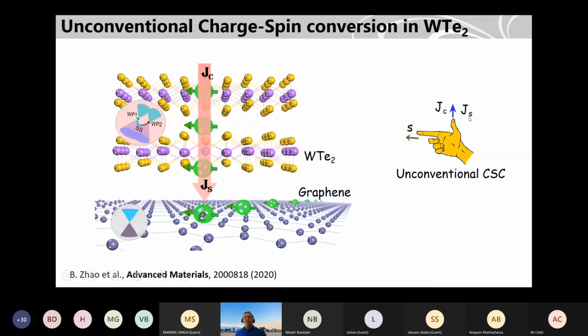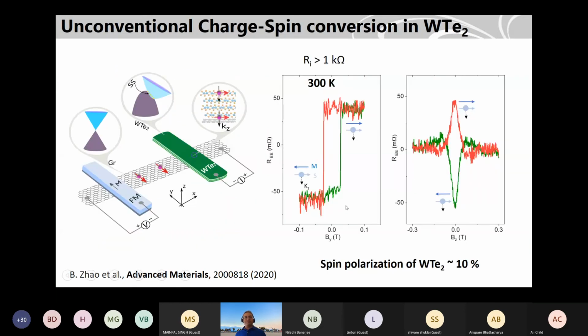Then we also observe an unconventional spin Hall effect, which is due to a perpendicular spin coming, where the spin current and the charge current are actually parallel to each other. So the spin direction is perpendicular to this. Why do we call it unconventional? Because this is not expected in conventional materials, but it is possible in tungsten telluride because the symmetry is broken. So you can find other components of spin because of the broken symmetry.